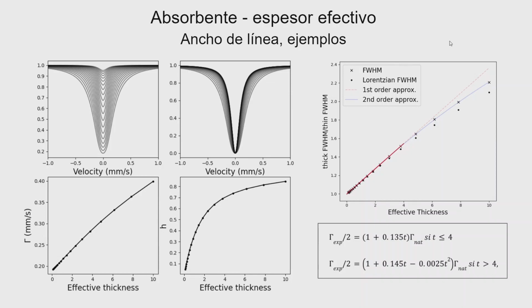This is a simulation where it is discussed exactly what the last slide was showing, that thickness effects affect the line width. So in this one, there is a normalization on the depth, and you can see that when you increase the effective thickness, the width starts to increase. In this one, there is not only an increase in the width, but also an increase in the depth. That is quite obvious because you put more sample and you have more absorption.